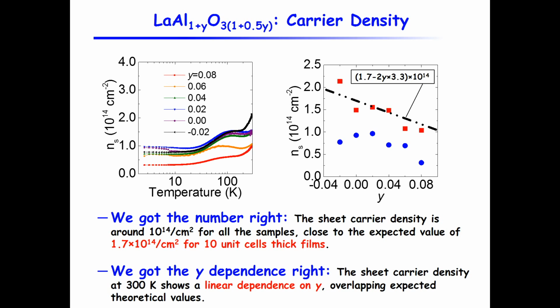The carrier density for all these samples is on the order of 10 to the 14th, and it does depend on the stoichiometry, as it should. Here we plot it as a function of the composition. This is the low temperature data, and this is the room temperature data.